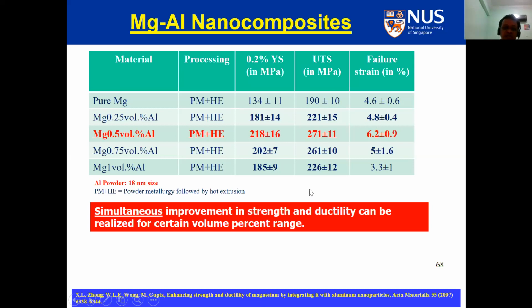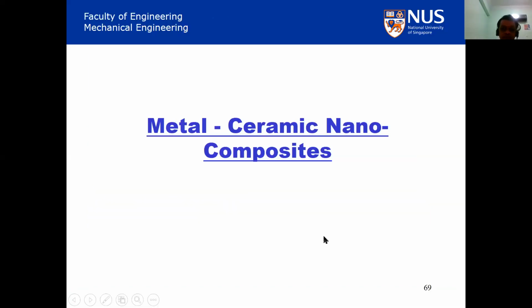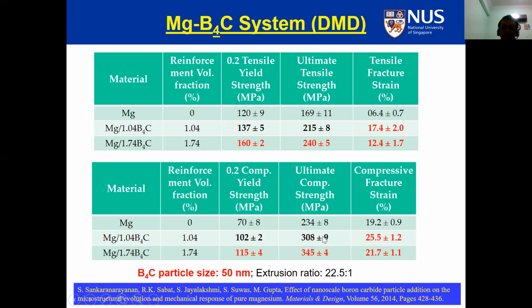And it is possible to disperse the metal particles, which are soluble, only because we use the microwave processing technique. We also use ceramics. I'll give you only one example. We have tested almost hundreds of types of ceramics.